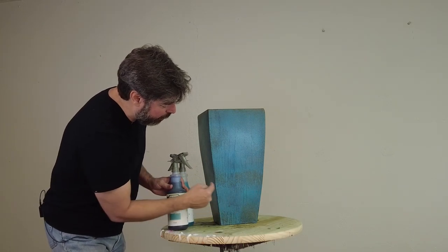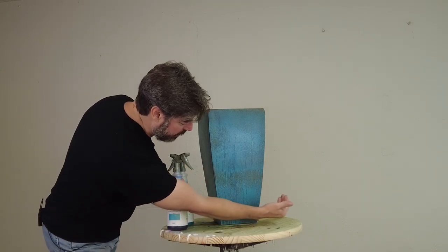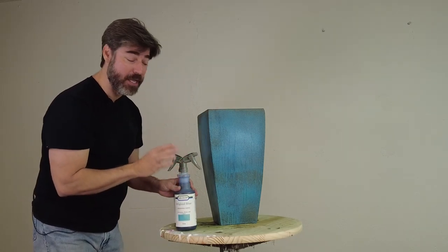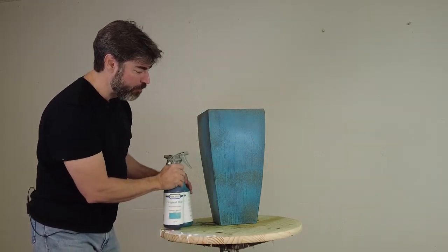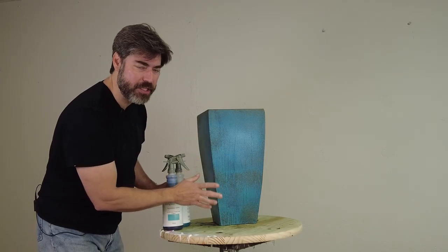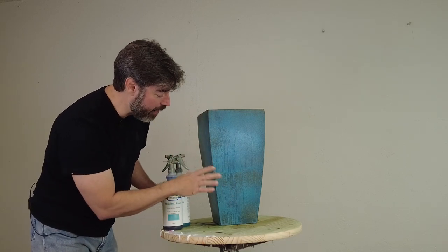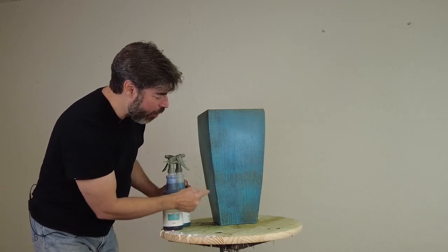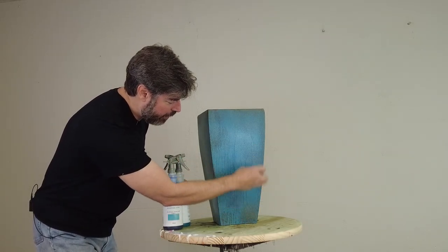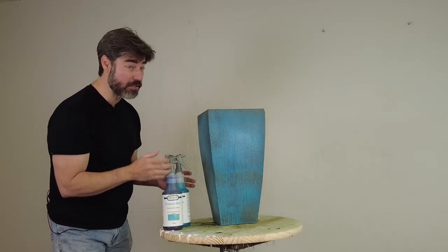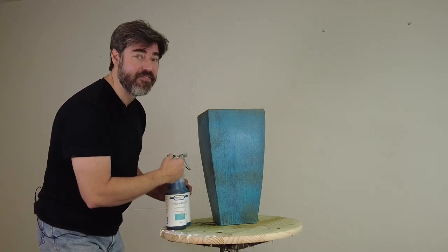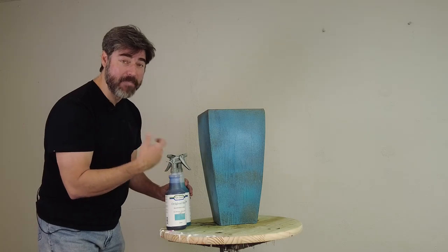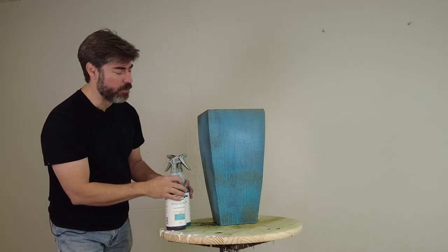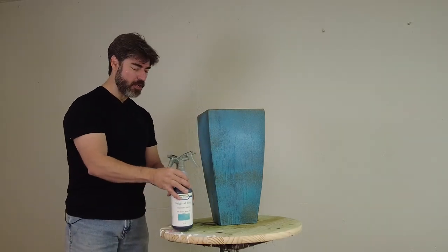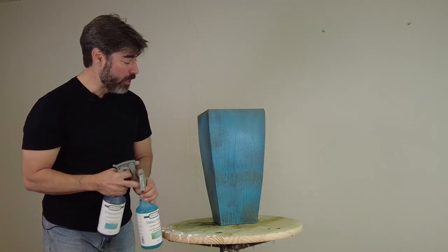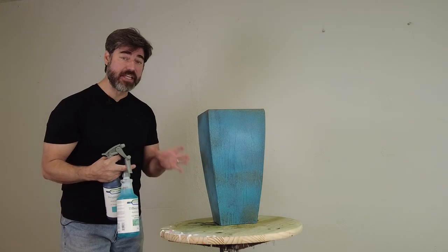In a little bit, I kind of got it there where you can see I did one pass with the blue and then came down here below, and we have that spot in between. So be mindful of that so you don't wind up with these funky areas. And I'm not 100% happy with this, but I'm not gonna mess with it until the whole thing dries, and who knows, it may dry just fine. But this is a good example of, I over applied that just a little bit, and you can see some of those runs, which sometimes complements the look, sometimes it doesn't. And just be very careful. You're obviously not gonna see a reaction immediately, so don't keep spraying until you see a reaction, or you can wind up with all kinds of drips and over application. So we're gonna go ahead and let that sit and develop. And then once this is completely developed, that's where we'll apply our sealer to lock all of that in.